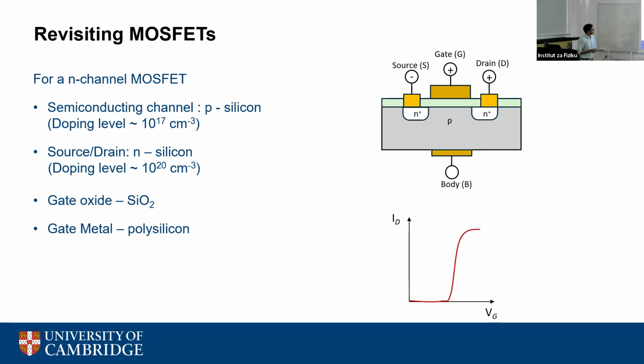But what is interesting to know here is what the materials involved are. In a basic silicon transistor, if you have an N-channel transistor, you have P-type silicon with a doping level of around 10 to the power 17 per centimeter cube. You have source and drain with a doping level of 10 to the power 20.